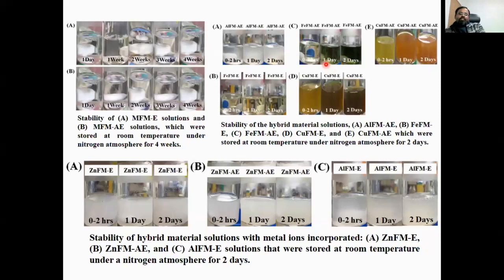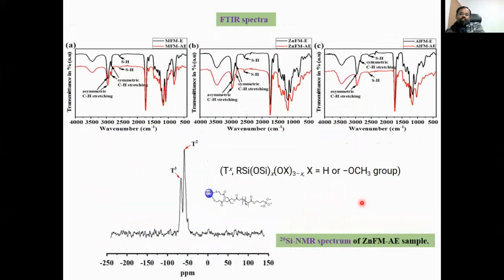In this case, with iron we encountered some problems, and we also used copper. The transparency is also not so good, and when we use aluminium and zinc, transparency is not so good, but dispersibility is good. And then we can make this stable solution, but we should be cautious about moisture, because this material is quite sensitive to moisture, so we maintain it under argon or nitrogen atmosphere. When required, we can take out the solution and immediately coat. We also have to be careful, because it sometimes gels after exposure to air for a longer time, so we should take more care when developing these materials.